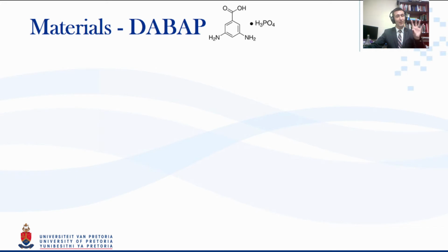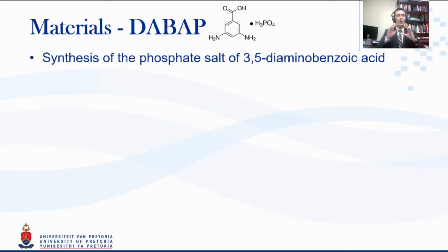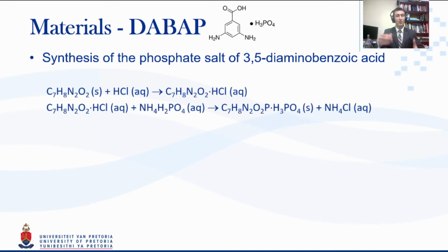Here is where I talk about the novel product we designed. One of the reasons that we theorized the production of this material we call 3,5-diamino benzoic acid phosphate is that this material that it's made from, diaminobenzoic acid, in a study quite a while back was used at the University of Pretoria as a filler in some polymeric material and seemed to have some naturally flame retarding abilities. We then combined this with the general thinking that phosphate groups cause very good intumescent behavior.